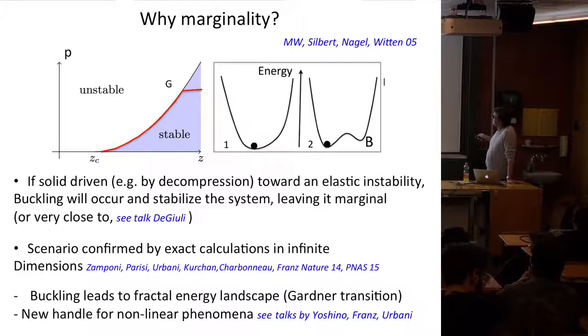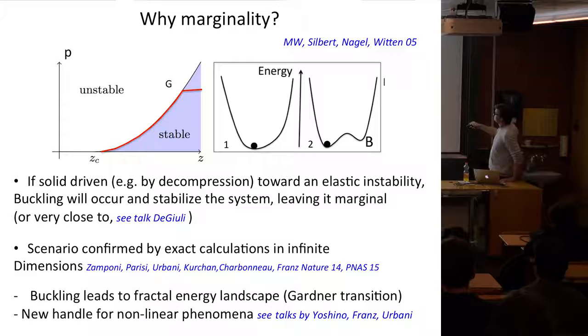So this scenario was the recent result that came from those authors. Many of them are actually in the room. And they could do exact calculation in infinite dimension. And what they could first show is that they found the same. Actually, it was not in infinite dimension for packing. It was a perceptron model where you have frozen disorder. But in such systems, they could actually first show that the relationship between pressure and Z was the one predicted here. They could also compute the spectrum and have the same signature of the spectrum of marginalities that we had discussed, for example, this behavior. So in terms of vibrational physics and linear physics, it seems to be completely consistent.